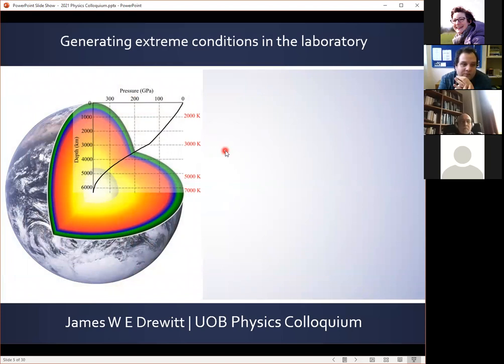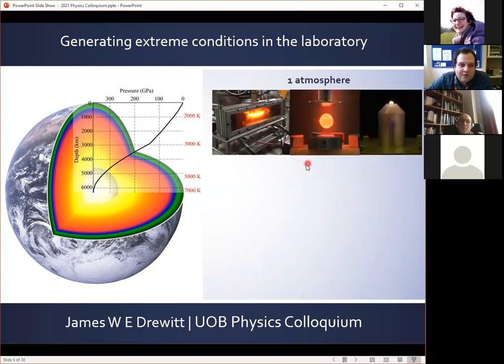So it's not possible to access directly the extreme conditions, obviously, in the deep Earth and deep planetary interiors. And so to probe a liquid structure, it's necessary to reproduce these extreme conditions in the laboratory. So at 1 atmosphere pressure conditions, we can generate high temperatures using conventional furnace methods or wire heaters. Or for very high temperatures where it's impossible to contain a sample, for oxide melts or metallic melts, for example, we can use the method of levitation with laser heating.